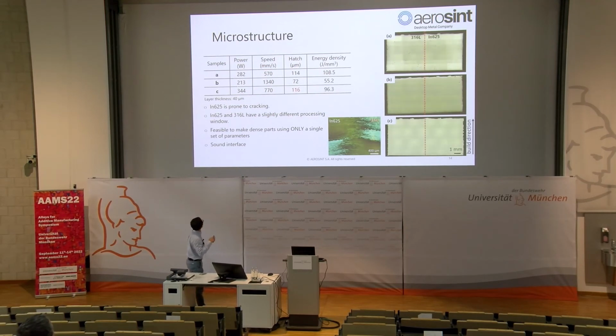So as I listed, these are the three parameters which we use. You can see that at the high energy input, we have quite a lot of defects on both materials. And then in the middle, it's the low energy side. The stainless steel looks fine, but in the Inconel there are still some defects. But at parameter set C, intermediate energy input, we can see that both materials are dense. And this set of parameters gives the highest productivity as well.